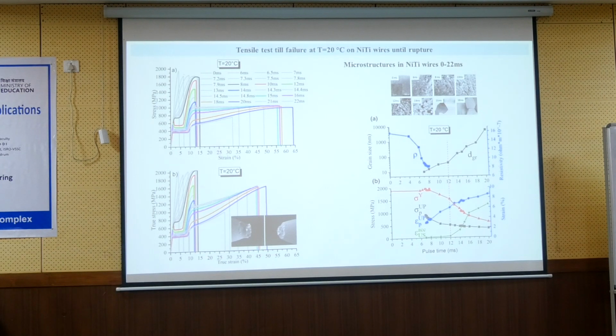Time. Millisecond applies for Joule heating, for electric heating. This applies, yeah. So the Joule heating is made to change the microstructure, to heat treat the material, just like if you put it into the furnace.